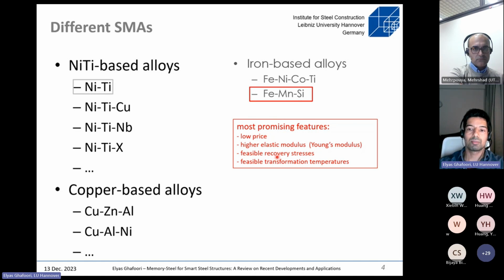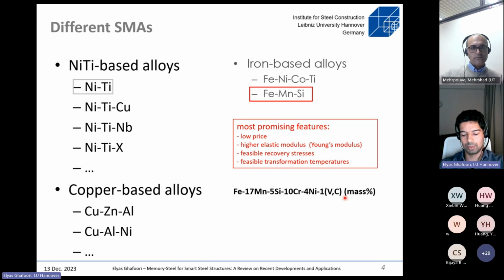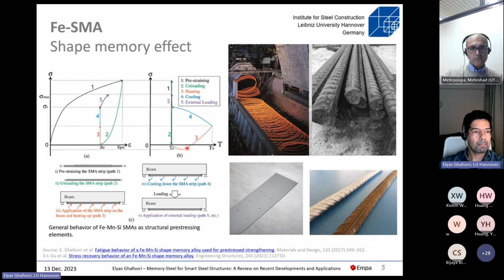And also the transformation temperature for a feasible recovery stress has been set to those that are feasible for construction. In construction, normally we deal with temperatures that are between -30 to plus 70 or 80. This is the exact composition you see here. From 2018, there is a company called Refer that is producing this alloy commercially, and that's the only shape memory alloy that has been commercialized so far.